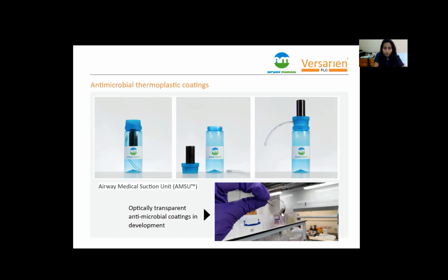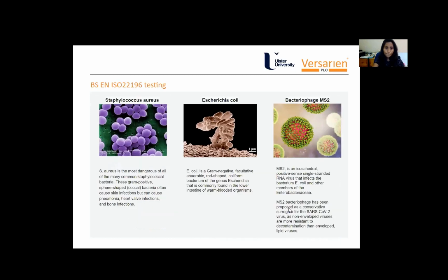And here you can see the coated plastic discs which we used later in the antimicrobial tests. They are transparent. Then we went into testing following the ISO 22196 standard. We tested these coated discs against Staphylococcus aureus, E. coli and bacteriophage MS2 strains. Staphylococcus aureus is a gram-positive bacterium which causes a wide variety of clinical diseases. E. coli is a gram-negative bacterium, and MS2 is an RNA virus which has also been proposed as a surrogate for SARS-CoV-2.